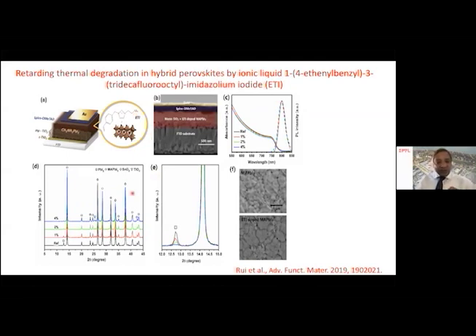Now, I'm just highlighting the XRD data of this particular material. Focus on the expanded version, figure E shown here. So this is the blank, which creates a lead iodide. This is a characteristic fingerprint of lead iodide, which is around 12.6 2 theta. Now, if we use 1%, that's the red line, the formation of lead iodide is decreased significantly. And if we use 2% of this ionic liquid, the formation of lead iodide from the perovskite composition is decreased much more significantly. With 4% of this ionic liquid, there is no formation of lead iodide in the perovskite composition. So this demonstrates the stability of the perovskite composition by using this ionic liquid.